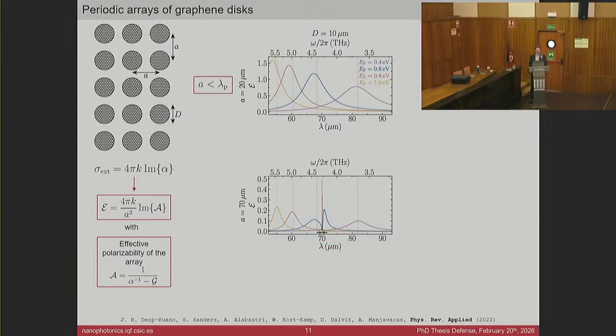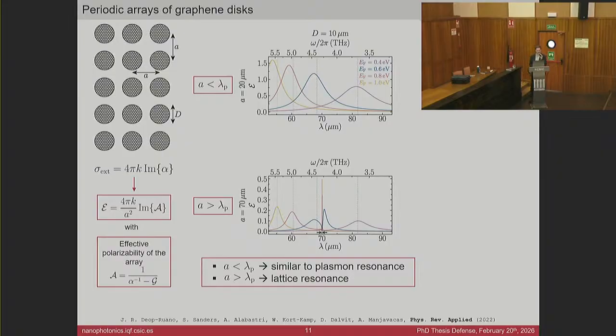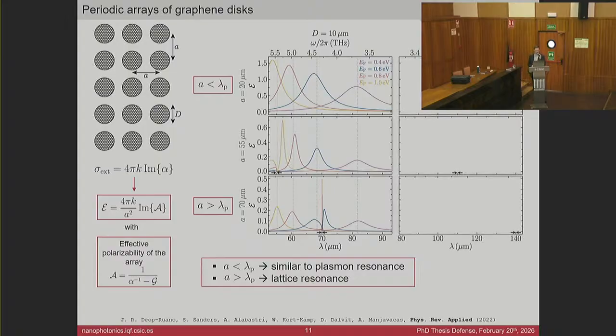It's going to cross the Rayleigh anomaly, and in this case, a new resonance with an extremely narrow profile, so narrow that here it just looks like a line on this scale, arises. And this happens for a period that is larger than the wavelength. So this indicates our condition for sustaining a lattice resonance. We need a period that is larger than the resonance wavelength of the individual nanostructure. I also analyzed some intermediate cases, where we can see this transition to a more collective mode, and also some results for a different diameter, where we again have a regime in which we support some resonances that look like localized surface plasmons, maybe a bit modified by first neighbor interactions, and we move to a regime in which we have lattice resonance, and even in this case we have some second order lattice resonances.